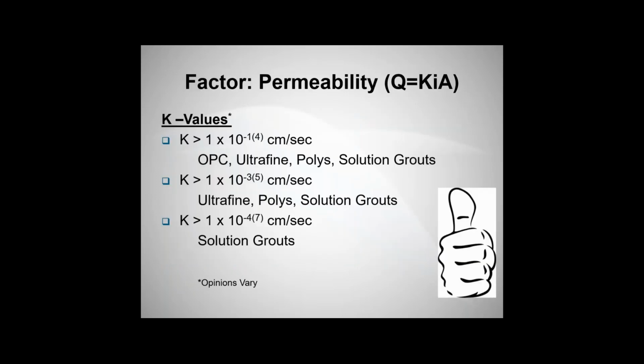The next factor is permeability. Q equals KIA. Q is flow, K is the permeability value, I is a factor, and A is the area. So when you're looking at the permeability K values at a range of 10 to the -1 to 10 to the -4 centimeters per second, that's going to be fairly permeable. So now we're looking at the same thing. Probably an ordinary Portland cement will be your first choice.